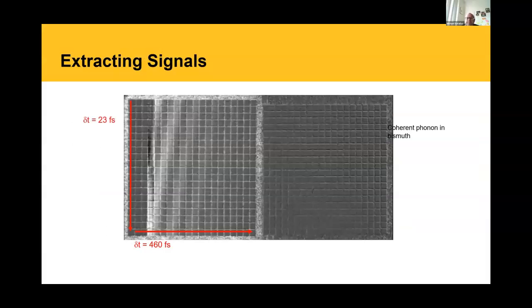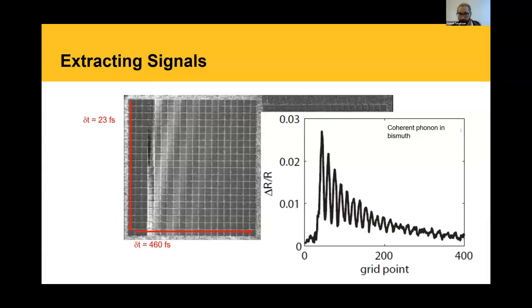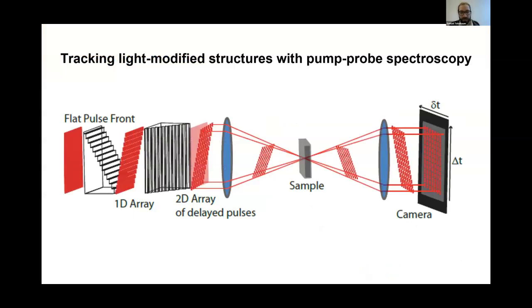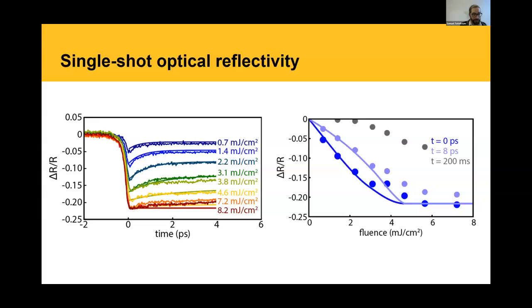Okay, so when you do these single shot measurements, essentially what you can see is if you image your echelons onto the detector and then take the average of each of them, then you can extract a single shot trace. And what we find is that the reflectivity drop, so this is the reflectivity drop as a function of time in picoseconds. And what we can find is we can connect now the amount the reflectivity changes with the switching threshold. And what you'll find is that the dynamic reflectivity drop saturates, as does the final photo switching threshold.